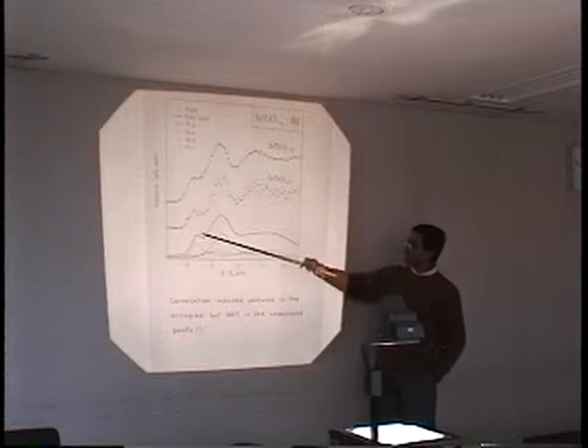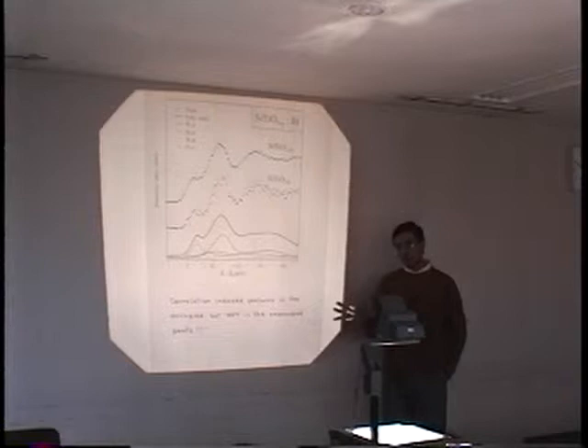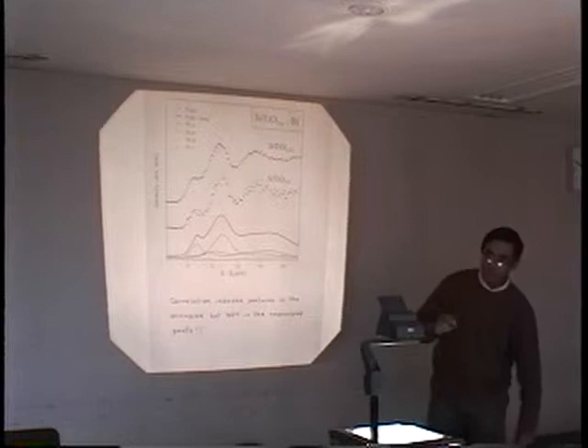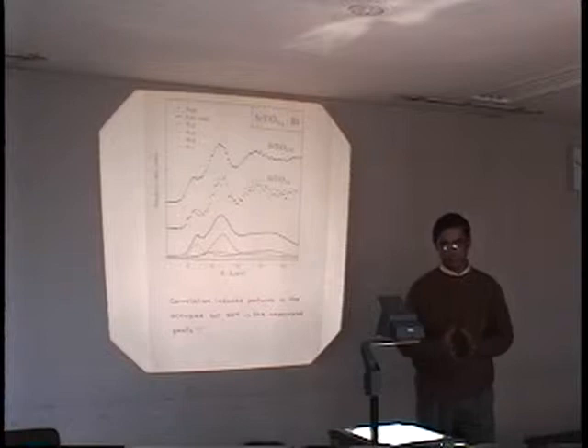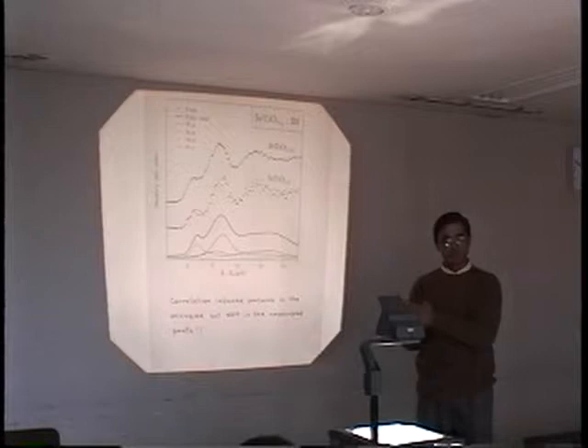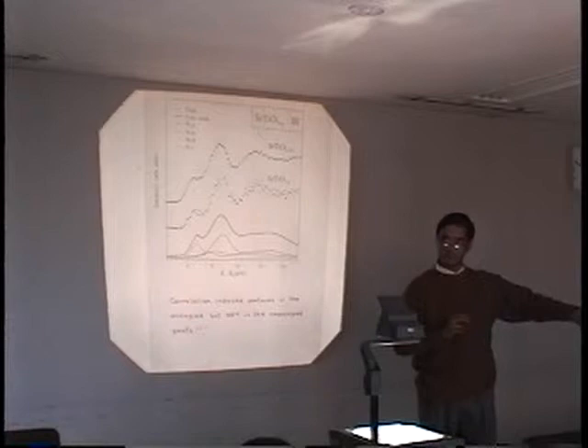And this is a completely unexpected result, because if you take any homogeneous model, Hubbard model would be one of those models, or any variation of that, and you do calculation of whatever sort, you will not find a situation when you have very small number of electrons that you get strong correlation in the satellite in the occupied part and no satellite in the unoccupied part.